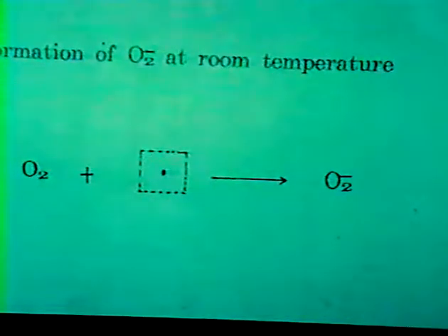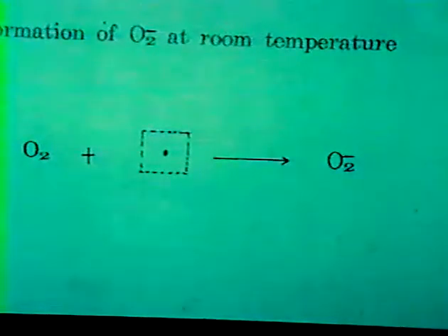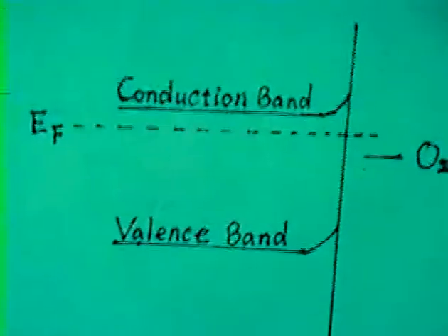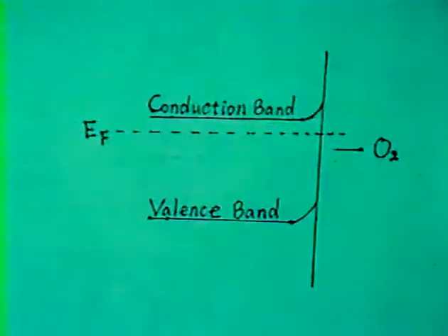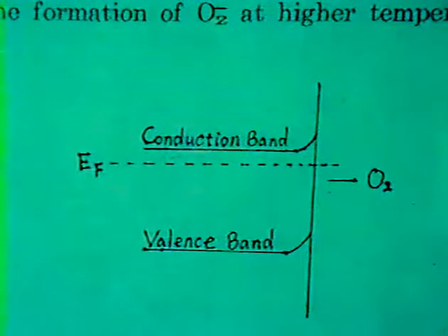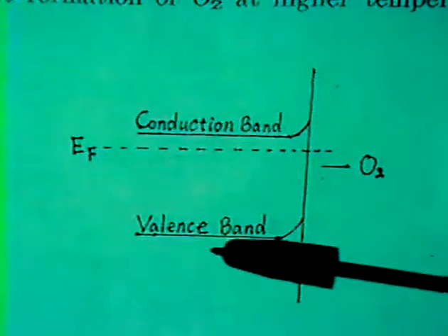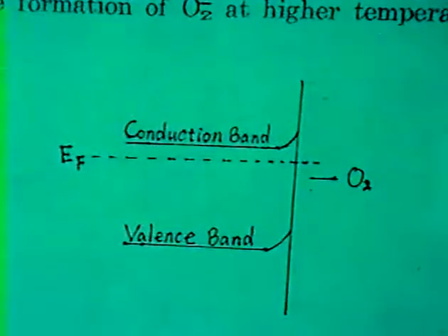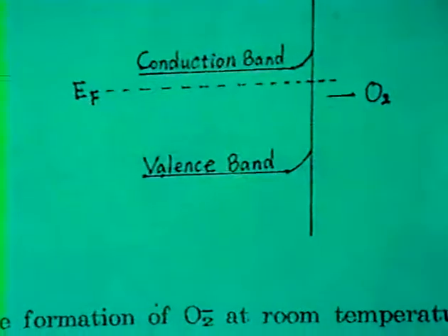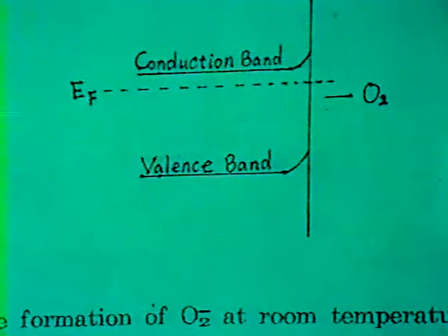We suggest that the oxygen species could be formed in two different ways, because the catalyst is a high temperature p-type semiconductor. So at high temperature, the electron in the valence band could be excited to the conduction band, and when the oxygen was introduced, the oxygen molecule could capture the electron excited by the higher energy, and led to the formation of superoxide species.